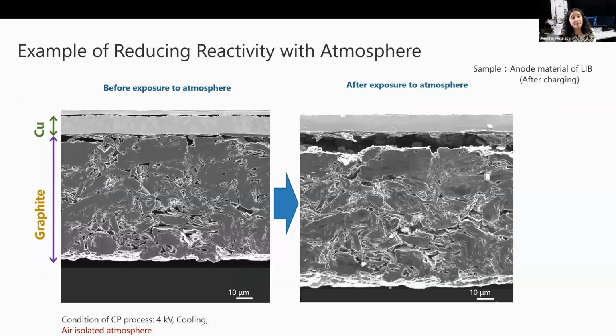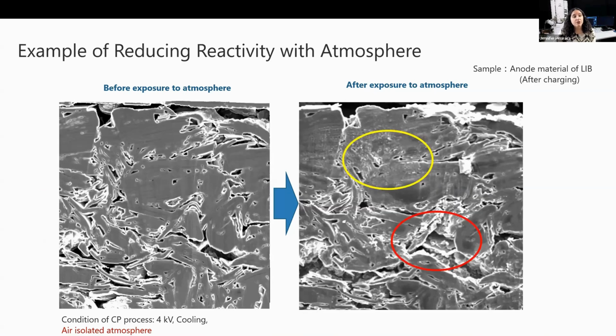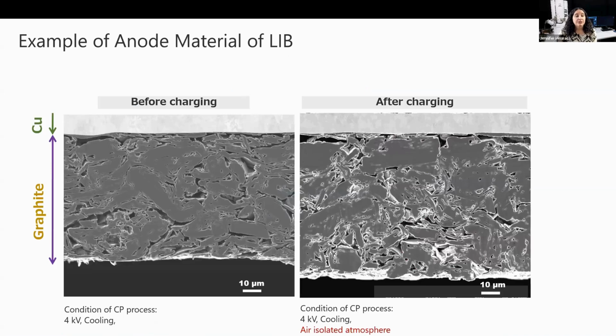Also, we examined the impact of atmospheric exposure on a cross-sectioned anode material after charging. So the SEM image on the right reveals a break in the interface between the copper and graphite, along with changes in the thickness of the graphite layer. At higher magnification, we see increased gap sizes between the graphite particles and signs of oxidation and surface deposits. So when comparing optimally prepared cross-sections of the same anode material before and after charging, only subtle differences in the graphite layer thickness are observed, thanks to the artifact-free preparation enabled by JEOL's cross-section polisher.